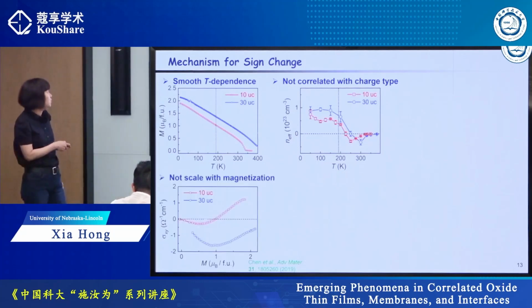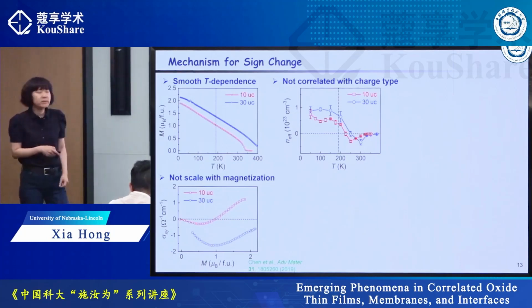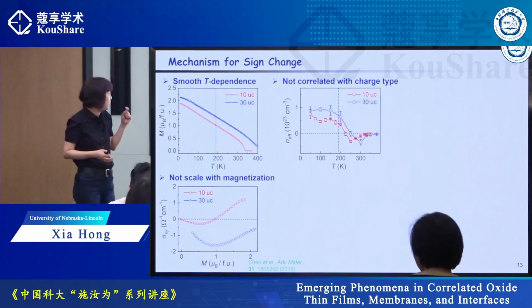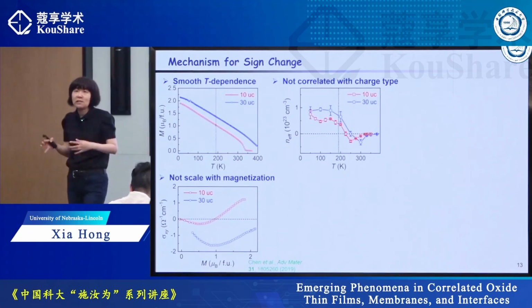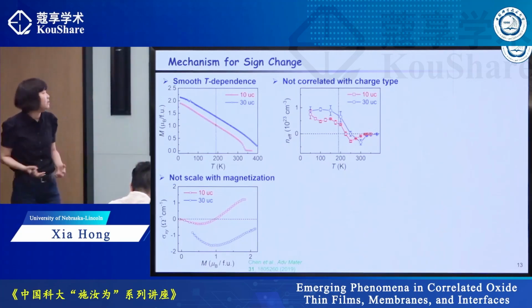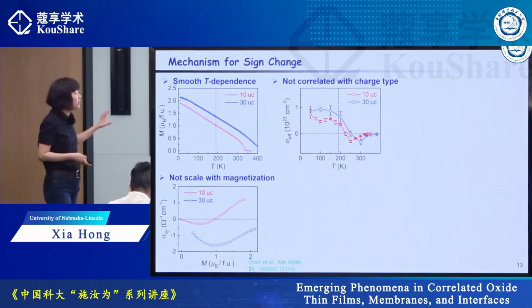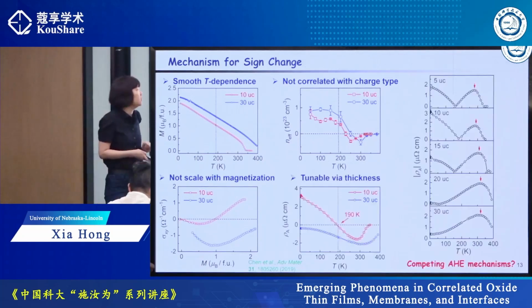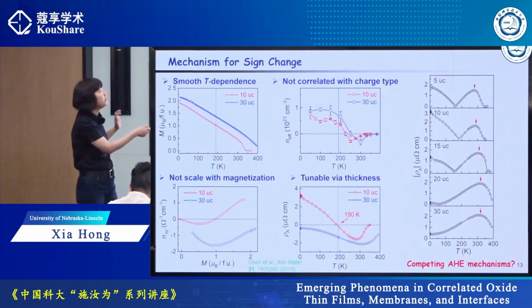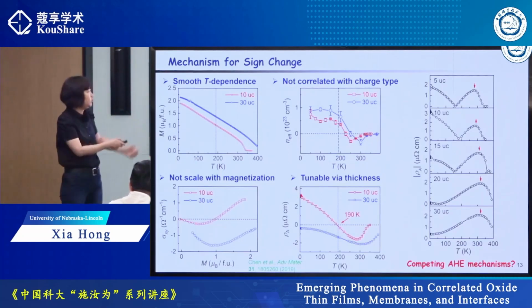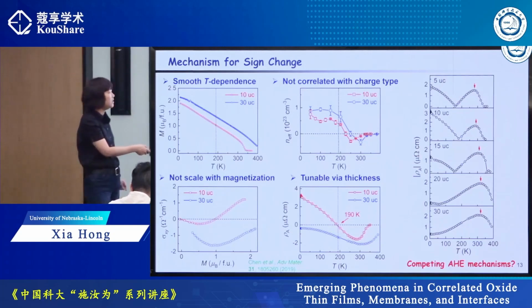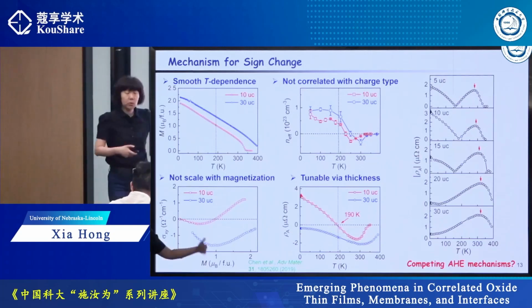And if you try to scale anomalous Hall conductivity with magnetization, there's no universal scaling behavior. So this means it's not like strontium ruthenate, where there's a magnetic monopole state. Here we have something probably more trivial. In fact, if we systematically study the amplitude of anomalous Hall resistivity as a function of temperature, you can see it's quite smooth.